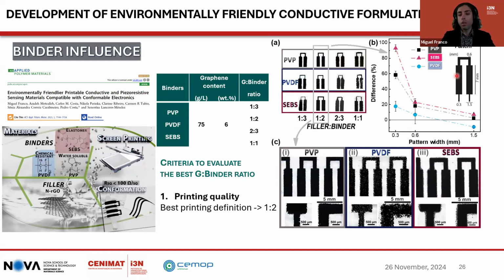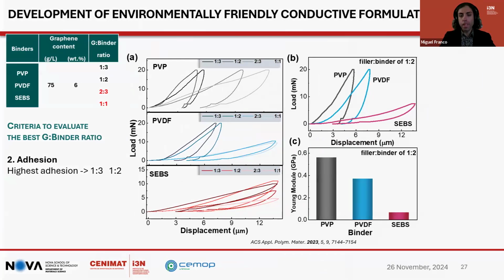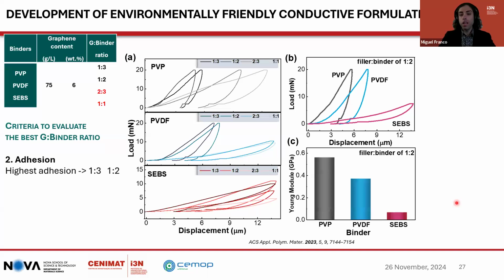It was found that the ratio of one graphene to two of binder showed better definition. When comparing the different polymers themselves, PVP showed better printing uniformity. The second criterion was adhesion, and here we can discard these two formulations which have a lower amount of binder. By analyzing the microindentation data, the displacement largely increases when increasing the graphene to binder relation from 1 to 2 to 2 to 3. When comparing the different polymers, PVP shows the best adhesion, with the lowest displacement and with the highest Young's modulus.